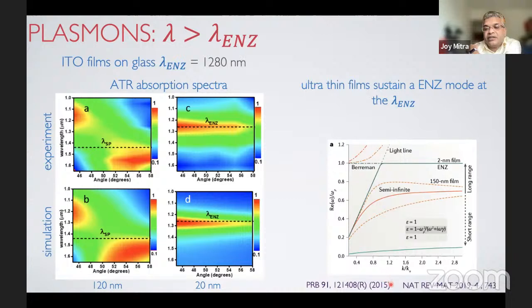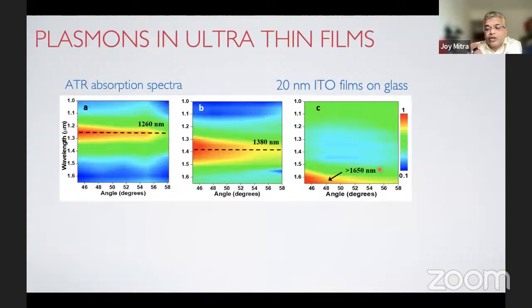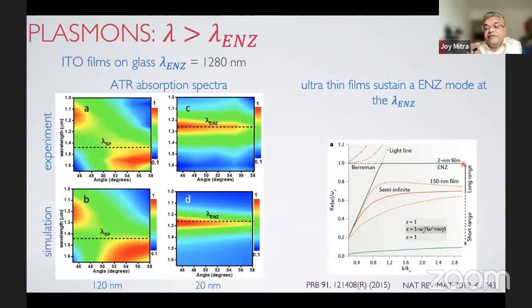We then figured out that in 2015 there had been some initial studies which said that if you decrease the film thickness, the plasmon dispersion relation, this solid curve here being the bulk plasmon dispersion relation, becomes almost flat, dispersionless, very close to the light line. Not only that, to the right of the light line you have this plasmon mode, and to the left of the light line we get radiative modes called the Berreman mode, which we will also discuss in a few minutes. For these very thin films, the plasmons will be excited exactly at the lambda ENZ. So if you change the lambda ENZ, the plasmon modes will also change, and they will be practically dispersionless, absolutely flat, which is what we were seeing here for a particular film, which had a lambda ENZ of 1280.